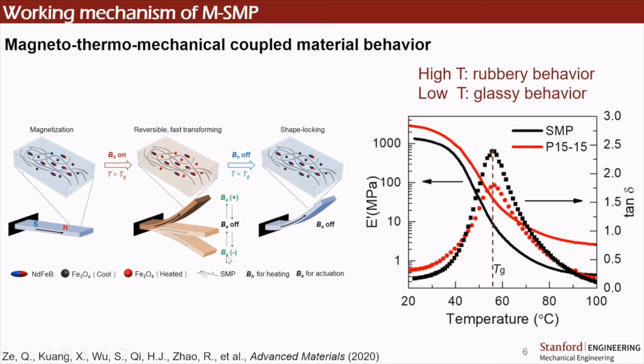So what we see over here is a mechanical characterization of the neat magnetic shape memory polymer and the shape memory polymer itself. There is a very important critical temperature here, called the glass transition temperature. If we look at the storage modulus, which is just the Young's modulus of the composite, at room temperature it's really stiff. It basically behaves like a glass, showing glassy behavior, with a Young's modulus beyond gigapascal.